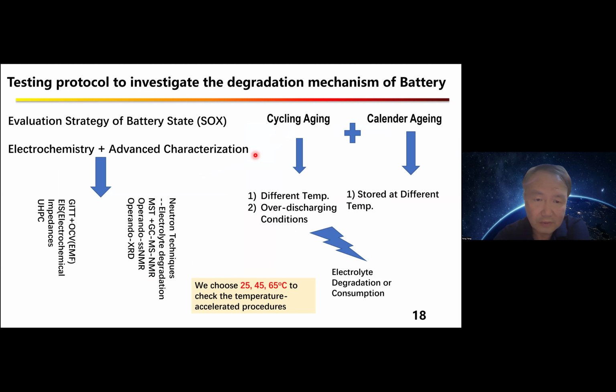So for the testing protocol to investigate degradation mechanism, I will show you in the next several slides. We want to evaluate the battery state of health, so we combine electrochemistry and advanced characterizations. We also check two types of aging modes: cycling aging or calendar aging, which are always met during aging tests. But we also choose three temperatures to check the temperature accelerated procedures.